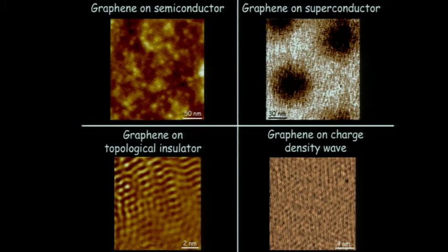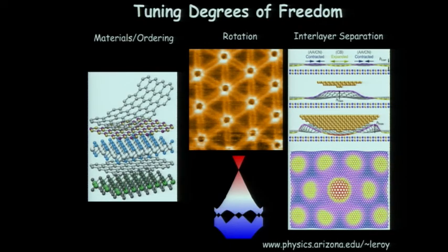My group is looking at a whole range of these different graphene heterostructures and trying to explore new physics in those. What I've told you about today is essentially that by tuning these three parameters, some new things can emerge in these van der Waals heterostructures: by tuning which materials you're using, the rotation between them, and also their interlayer separation. If you can get away from the equilibrium separation, you can induce new effects.